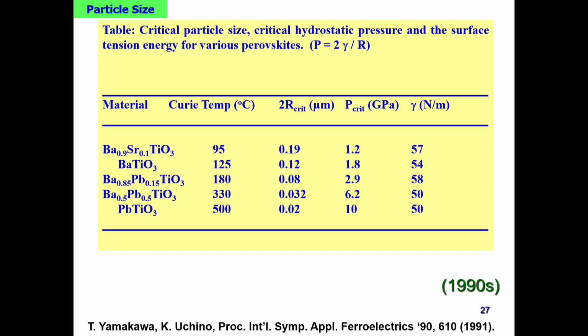So we expanded in the late 80s from barium titanate to barium strontium titanate and lead titanate. So the Curie temperature differs from lower than 100 degrees up to 500 degrees. Accordingly, we determined the critical particle size. As I told you, barium titanate is 0.1 micrometer, but 0.2 is for the lower Curie temperature, and 0.02 is for lead titanate. So with increasing Curie temperature,